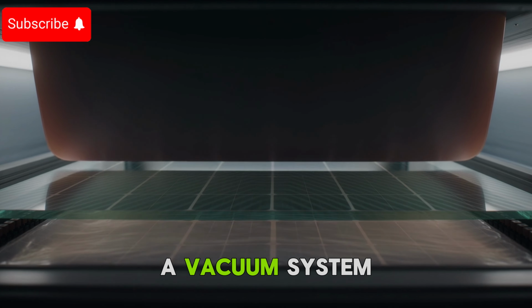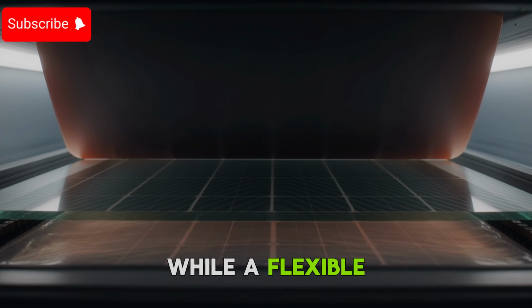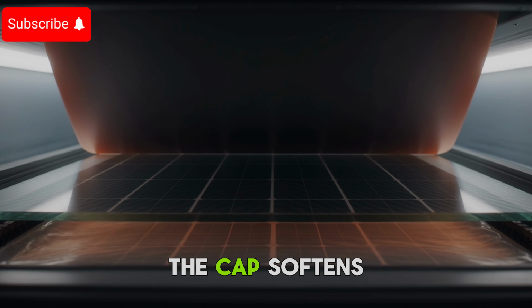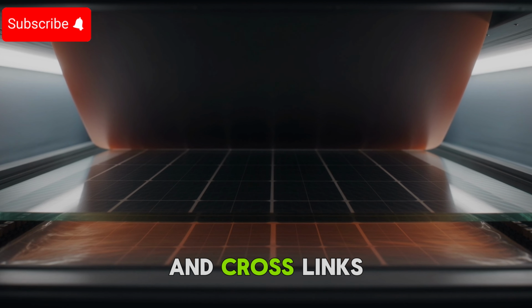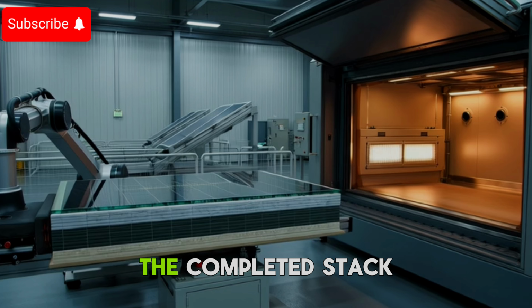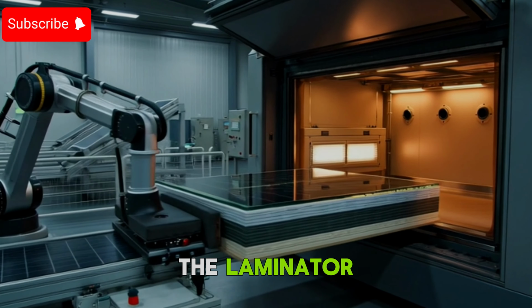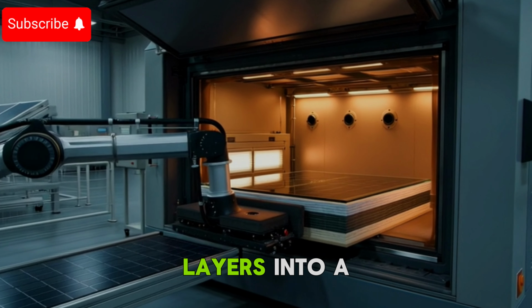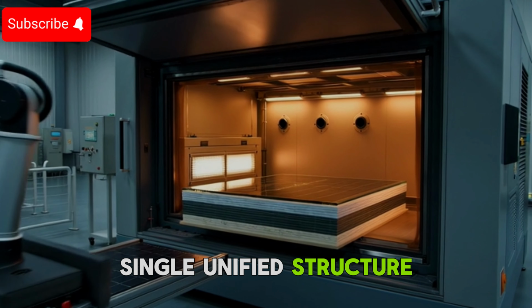Inside the laminator, a vacuum system removes all air from between the layers, while a flexible membrane presses down. At around 150 degrees Celsius, the encapsulant softens, flows into every space around the cells, and cross-links into a permanently bonded waterproof matrix. The completed stack is transferred into the laminator. Heat and vacuum will bond all layers into a single unified structure. Once the door closes, the transformation begins.